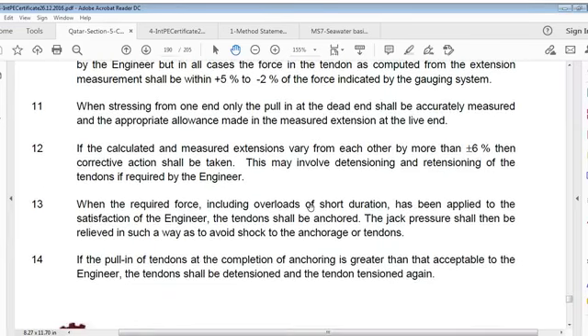When stressing from one end only, pull-in at dead end shall be accurately measured and appropriate allowance made in measured extension at live end. If calculated and measured extension vary from each other by more than plus minus 6%, then corrective action shall be taken. This may involve detensioning and retensioning of tendons if required by engineer.